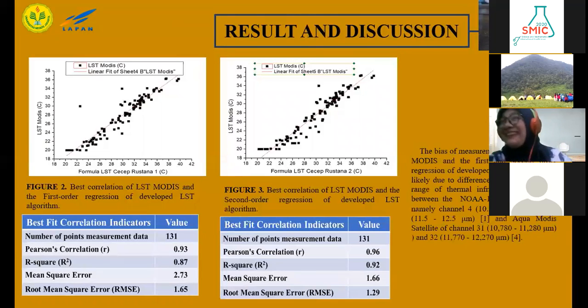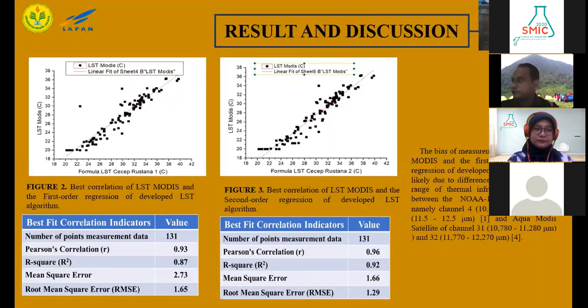The bias of measurement between LST MODIS and the first and second order regression of developed algorithm may be likely due to differences in the wavelength range of thermal infrared channel used between the NOAA 11 or AVHRR satellites, namely channel 4 of about 10.5 to 11.5 micrometers and channel 5 of about 11.5 to 12.5 micrometers, and Aqua MODIS satellite of channel 31 of about 10.7 to 11.2 micrometers and 32 of 11.7 to 12.2 micrometers.